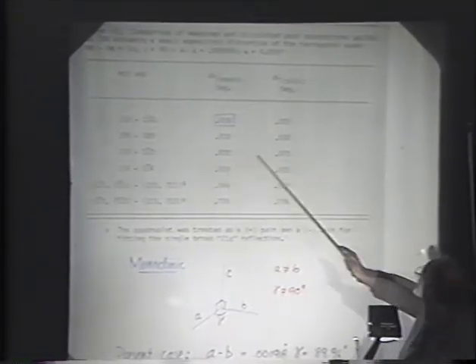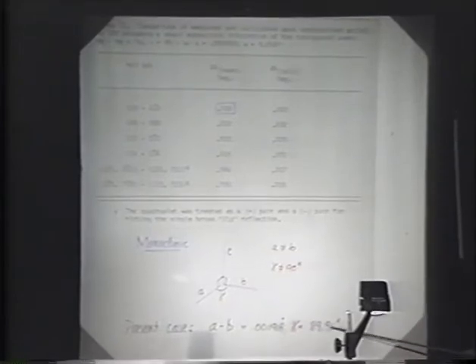So I'll just finish up with this. It's too bad that I cannot show you the single crystal data because they're beautiful. But the amount of broadening is consistent between measured and calculated. It's consistent with a monoclinic distortion, where gamma would be 90 degrees for orthorhombic. It is now 89.96, and the difference between A and B is of the order of 0.02 angstroms. So it's a very small monoclinic distortion, but it's not orthorhombic. And it is our suspicion that some of the transitions which have been identified as orthorhombic from tetragonal to orthorhombic in the strontium and barium substituted phases are indeed monoclinic.